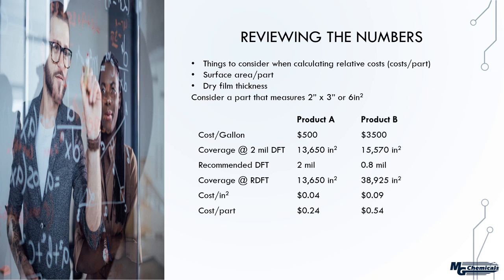Now let's compare that to a premium product, product B. Product B comes in at $3,500 a gallon. But we need to compare apples to apples. So we start with the coverage at 2 mil dry film thickness. We use the same dry film thickness as we did in product A, just to get that comparison. So right off the bat, we can see that it's closing the gap somewhat in terms of the cost difference because it's slightly more efficient. You can cover a slightly bigger area at 15,570 square inches.